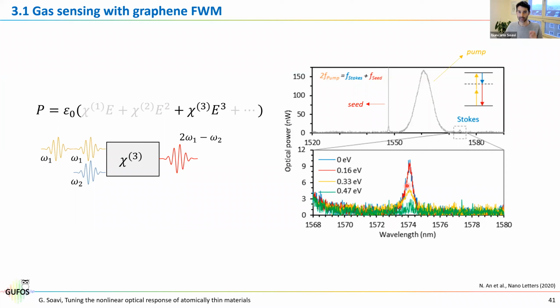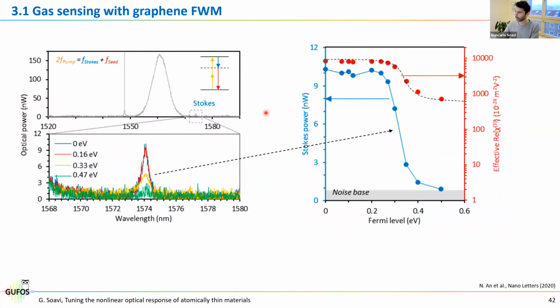And interestingly, in the same way that we saw for the third harmonic generation, this Stokes signal can be tuned by changing the Fermi energy. So as we now change the doping inside graphene, we can modulate the efficiency of this four-wave mixing process. Okay, how can we use this? We do the following. First of all, we characterize the Stokes power, so how the four-wave mixing is changing as a function of the Fermi level. Now, the situation here is slightly different compared to the third harmonic, because you see that the signal is maximum when we are at 0 Fermi level. It drops down when we are at this h bar omega equal to EF, and then it goes close to 0 when we are at large values of the Fermi level.